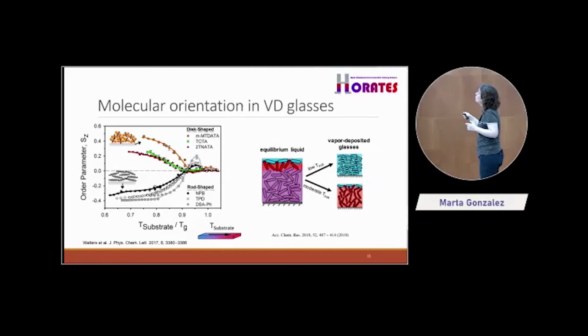But if you go to the surface of this sample, you will see that you have a certain layer where the molecules tend to stay slightly perpendicular. And if you go to really the surface, on top, then the molecules tend, this is a problem of van der Waals force, etc., the molecules tend to stay flat.